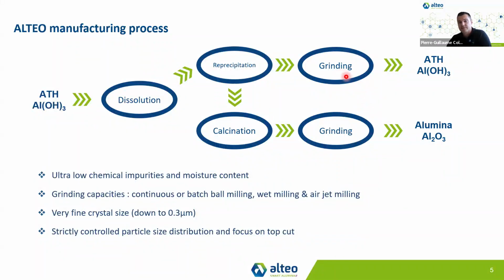We can either grind the product to get different levels of fineness for ATH, for thermal conductivity or flame retardant applications. The other option is a calcination step, where water is evaporated at a very high temperature. We have a huge rotary kiln of around 100 meters long and 5 meters in diameter. Then it can also be ground down to very fine particles, down to 0.3 microns. Today we have different grinding capacities with continuous batch ball milling, wet milling, and airjet milling. We pay particular attention to the coarse particles and the top cuts.